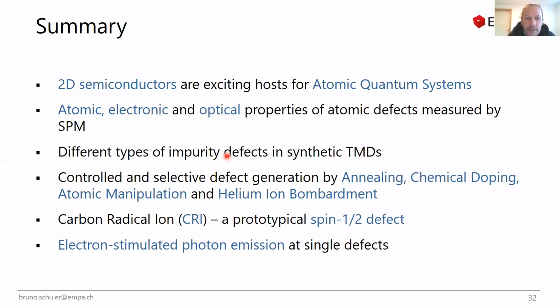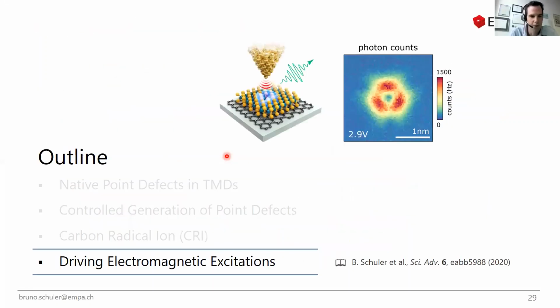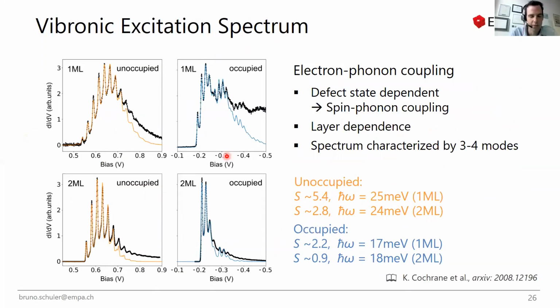So my question is, can you extract the lifetime of these states on the top and bottom layer, and what order are they? So there, I mean, we could. And it's also what we did, just from the broadening. So if you assume the entire broadening is due to lifetime limiting.